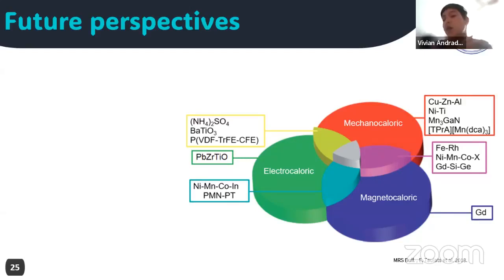And for nickel manganese gallium, for instance, the Martensitic transition depends on the ratio between manganese and gallium, and is around room temperature. So we have the largest entropy change, magnetic entropy change. So these are the materials that we are looking for.